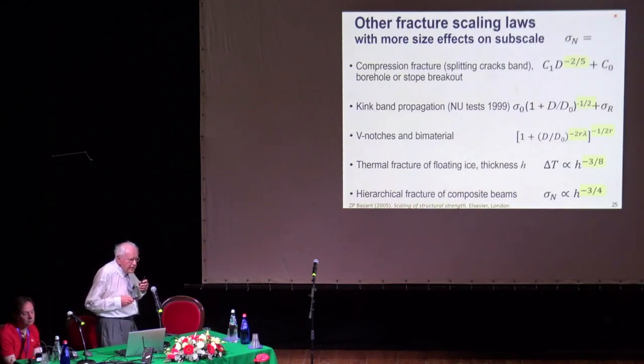Now, there are more complicated cases where you have some phenomenon with size effect on the subscale. For example, buckling can produce that, buckling of splitting cracks in the materials. Then you can get different exponents. So, for example, in borehole failure, exponent minus 2/5. That seems to agree with experiments. Kink band propagation in composites gives the same formula, but with an additional constant residual value, because the kink bands eventually yield with the buckling of the fibers, and that's size dependent. It's a fracture problem because they propagate.